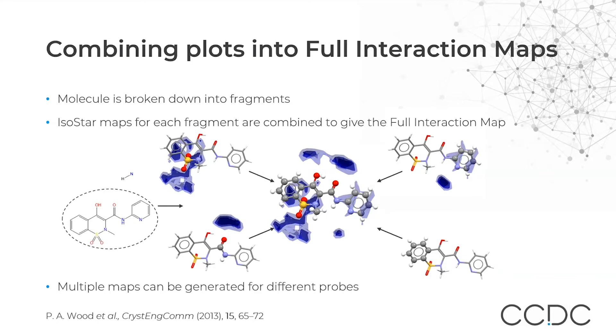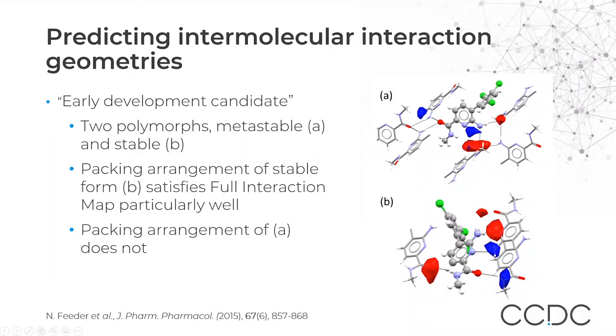You can also consider different probes beyond NH. This is an example of the use of full interaction maps for an early development candidate for a drug with two polymorphs: polymorph A, which is a metastable form, and polymorph B, which is the stable form. The packing arrangement of the stable polymorph B satisfies the full interaction maps particularly well, while polymorph A does not, giving insight into solid-form stability.